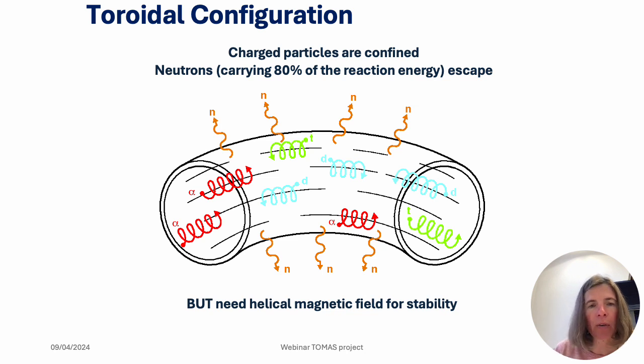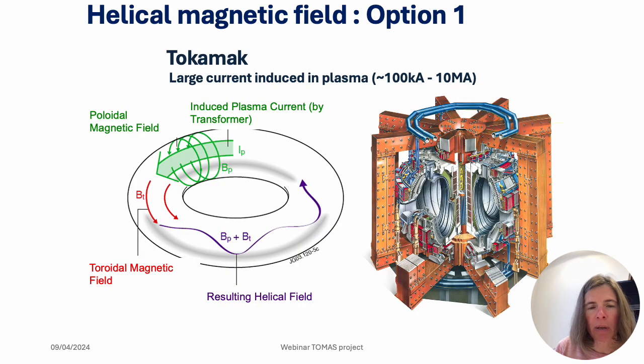So it's not completely true because of the bending of the donut, the magnetic field is not homogeneous anymore, and you create additional losses, additional drifts, where after a certain moment you will also lose particles. So this simple toroidal configuration is not a good solution. It has to be a bit more complicated. There are two solutions for that. In both cases, what you do is you create an additional magnetic field, what we call a helical field, a twisted magnetic field, a combination of the toroidal and a poloidal field. The two solutions, but I have no time to go into detail, are called tokamak and stellarator.